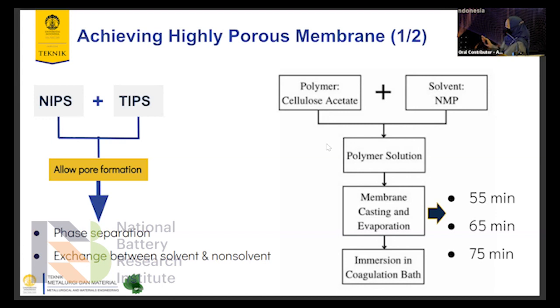The overall process is shown in this figure. We use cellulose acetate as the polymer matrix and NMP as the solvent. When we blend the polymer and the solvent, we will get the polymer solution. The stirring process to get the polymer solution is at 70 degrees, and then the polymer solution will be cast on a glass plate. So we will leave it so it can evaporate, and the evaporation time is varied at 55 minutes, 65 minutes, and 75 minutes. And then after the evaporation time, we will immerse the polymer membrane in the coagulation bath as the non-solvent.